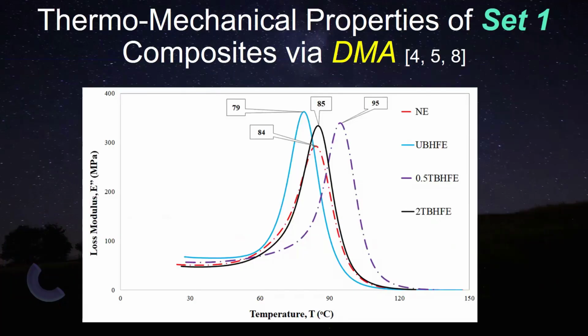Let's get to thermomechanical properties for set 1 via DMA, and you can see that the red color is denoted by neat epoxy. So the glass transition temperature I actually picked up from the peak of the loss modulus. It was 84 degrees centigrade. However, the untreated fiber is 79, reduced. With treated, it actually enhanced to 95 degrees centigrade. So with the treated fiber, it enhanced at some point. However, for 2 hours treated, it reduced. And 2 hours is a prolonged time, so a lot of cellulose was destroyed. That's why the value dropped again.